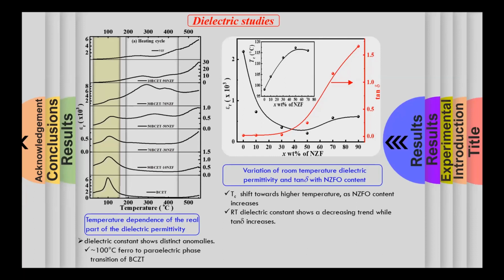Because when we talk about single phase multiferroic, it is very important that the ferroelectricity and the magnetism should coexist, like I showed in my slides. The ferroelectricity mechanism then becomes very important if you consider the single phase. But of course, if we have the multi-phase, then the problem will be that it will not be transparent, because when you add the ferrite, it will not be transparent. So in single phase, we have to be very careful of what ferroelectricity mechanism we are handling.